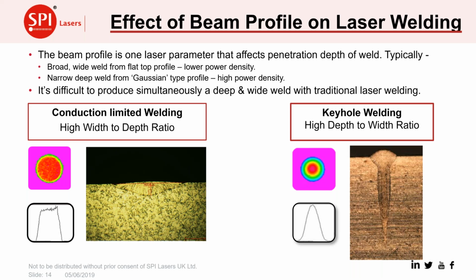If you look at the picture on the left, we've gone for one of those, let's say, large diameter fibers. We've produced a reasonably uniform power density going onto the surface of the workpiece, and we've produced a broad but shallow weld in the left-hand picture there. And if we go for a much smaller spot, particularly one where the energy is concentrated onto the center, then we get a keyhole weld. We produce a narrow and deep weld. What is difficult to do with traditional welding is to produce a deep and wide weld, which you might want if you're overlap welding and want a reasonably broad weld interface where the two sheets join, to give you a high strength weld. And we'll come on to that problem later on.